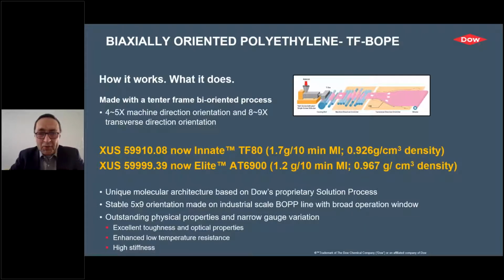Now, how does this process work to make thin, strong polyethylene films? First of all, you have a cast sheet extrusion, then you orient this film in a machine direction, then you orient it in a transverse direction, so it's a sequential process. Typically here the orientation ratio is 5, and here the orientation ratio is 9. So overall you have a 5x9 orientation. That means if you start with a film that is 700 micrometers thick, you end up with one which is about 20 micrometers thin. So orientation ratio of about 40. The final film is 40 times thinner than the initial film.